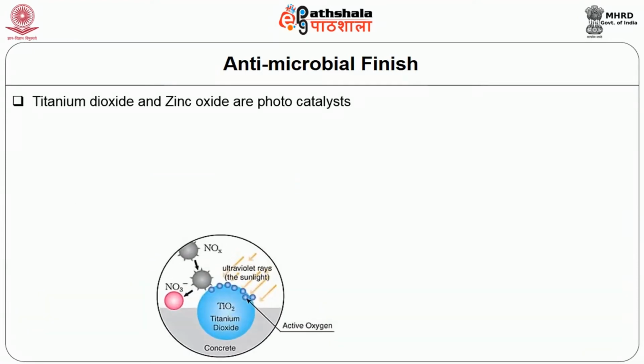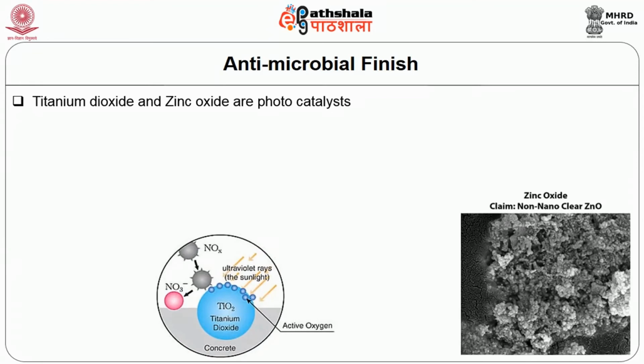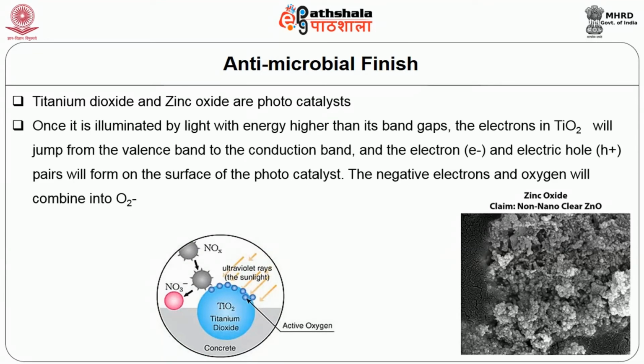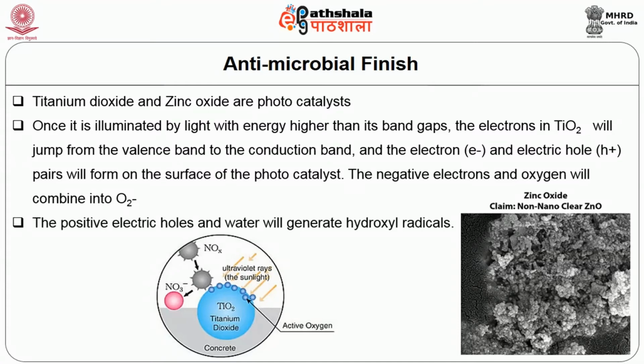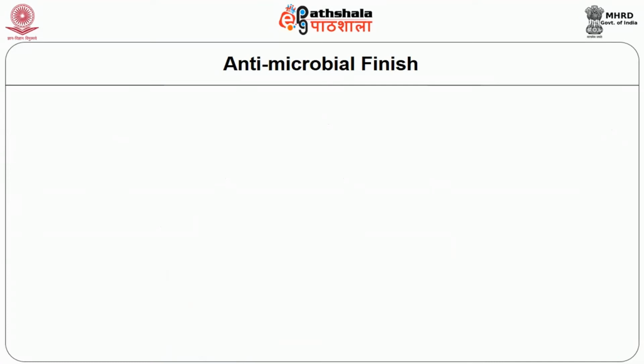Titanium dioxide and zinc oxide are photocatalysts. Once it's illuminated by light with energy higher than its band gaps, the electrons in titanium dioxide will jump from the valence band to the conduction band, and the electron and electric hole pairs will form on the surface of the photocatalyst. The negative electrons and oxygen will combine into oxygen ions. The positive electric holes and water will generate hydroxyl radicals.